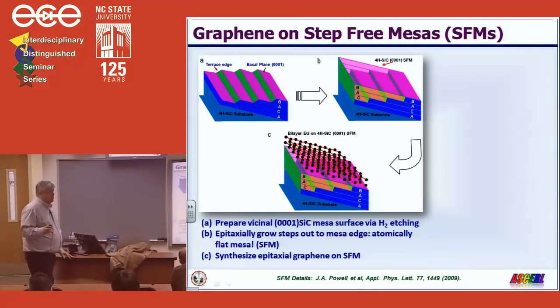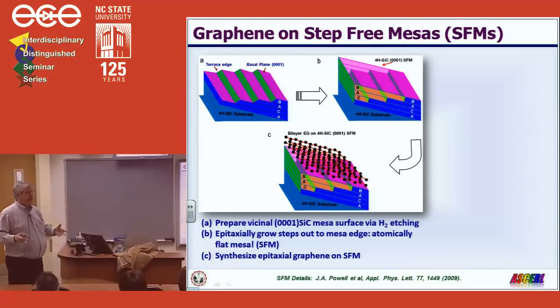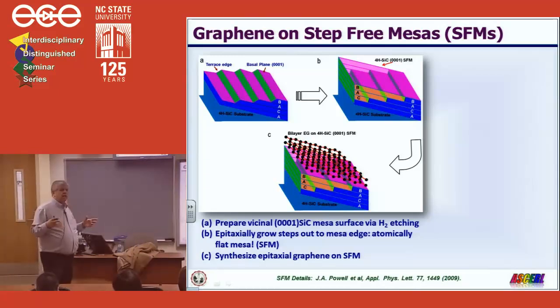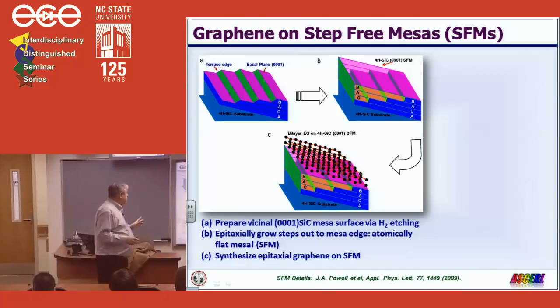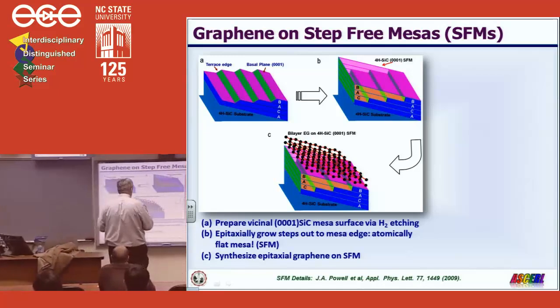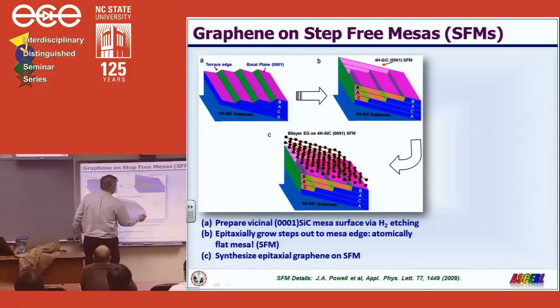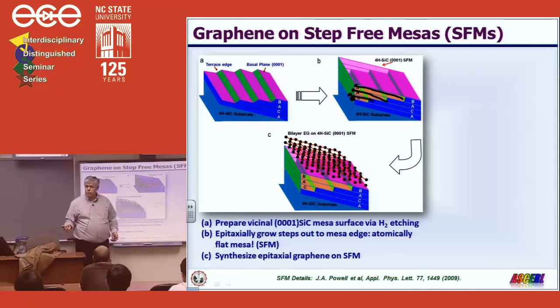One way of doing this is to take silicon carbide, and I can form mesas on it ahead of time. These don't have to be tall mesas, 1 to 2 microns. And what I will do is I will use silicon carbide epitaxy, and I will grow the steps out until I reach the edge of the mesa. Now what will happen is, at the edge of the mesa, atoms have nowhere to hang on. And so there will be no further epitaxial growth, no further nucleation. And so growth will stop.